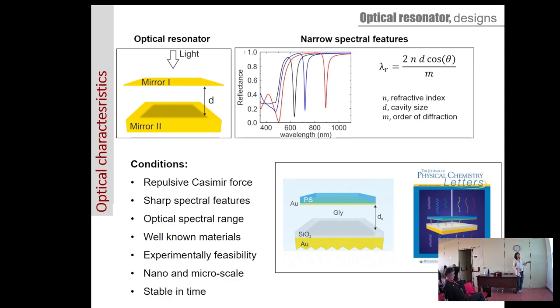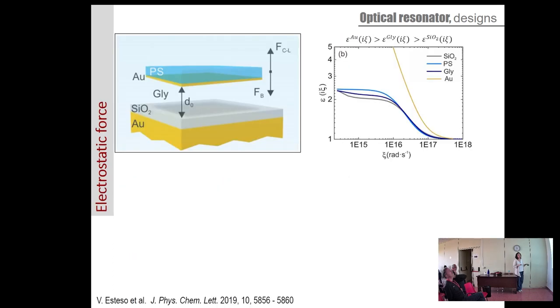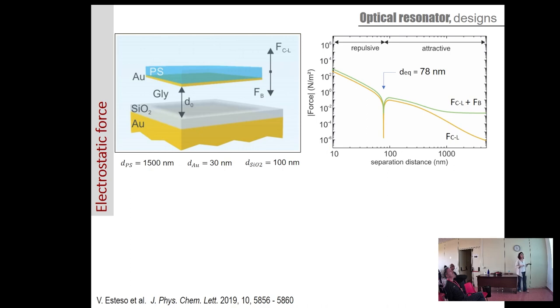So the final design is something like this. We have a gold substrate covered with a thin layer of silica, on top of which we have this bilayer of polystyrene and gold, all immersed in glycerol. So here we could see that these permittivities fulfill the equation that I told you before. And when we have a look at the force acting on this system for this set of parameters as a function of the separation distance, in logarithmic scale, we can observe that we have a repulsive component at short separation distances that changes to be attractive at longer ones. And when we have this zero force, we have this minimum, and this corresponds to the equilibrium distance.